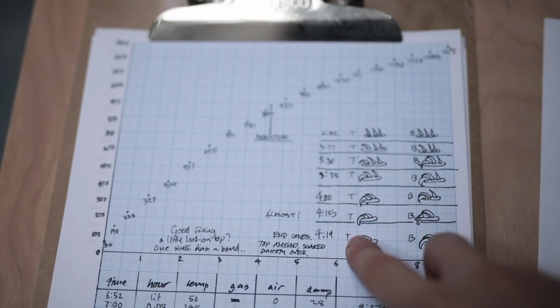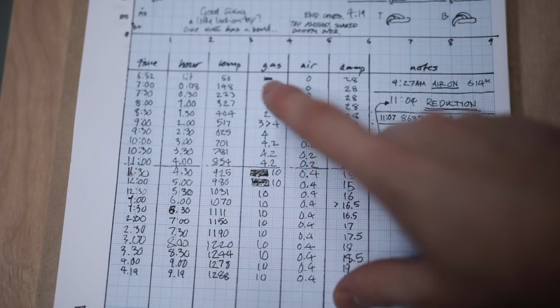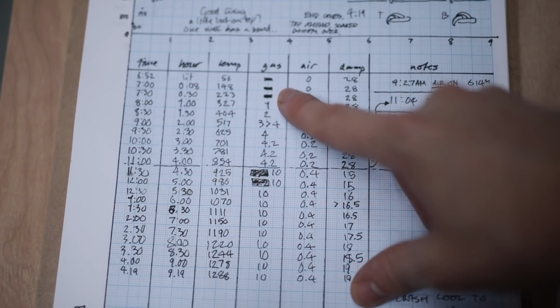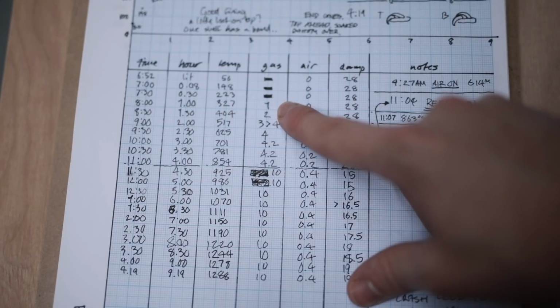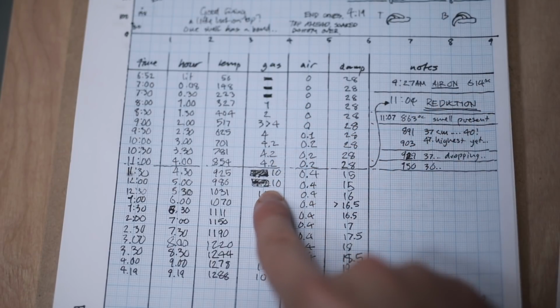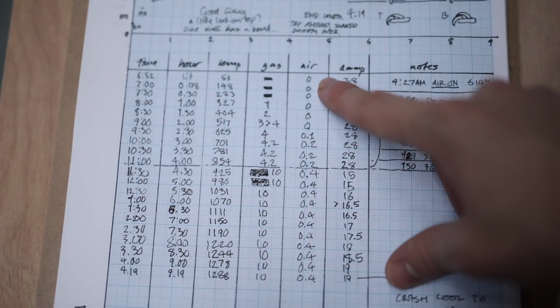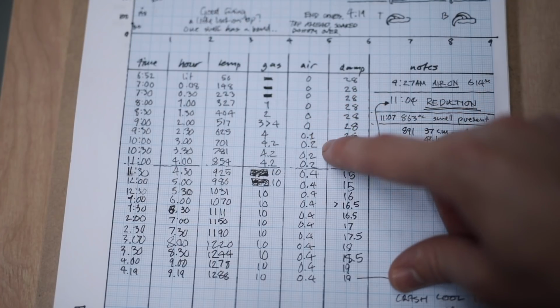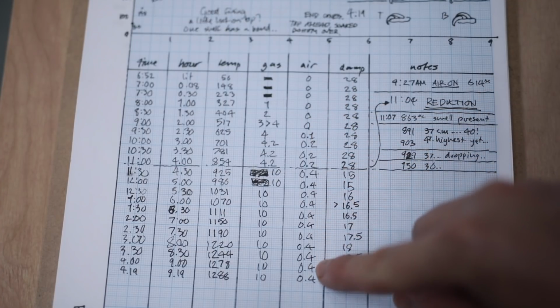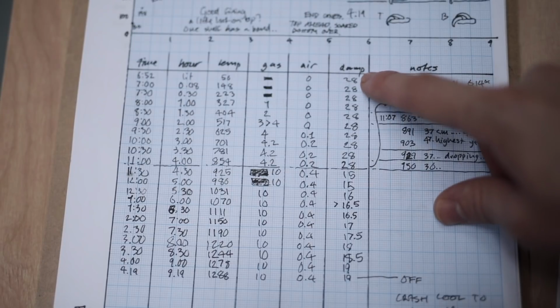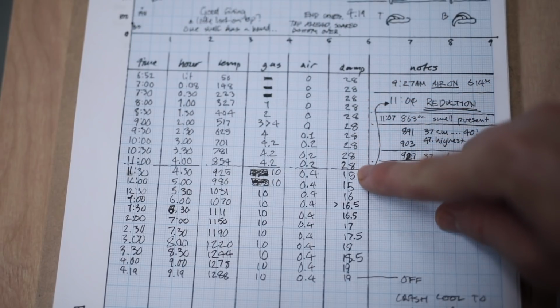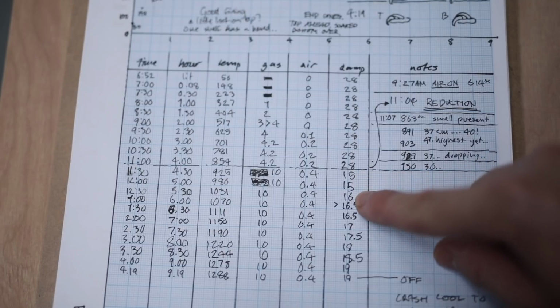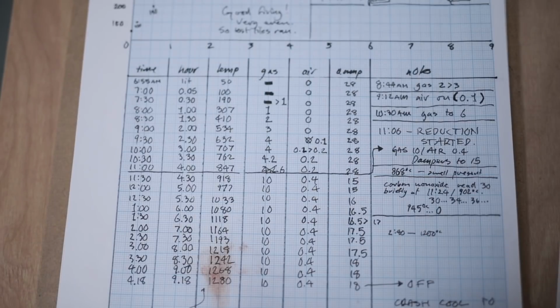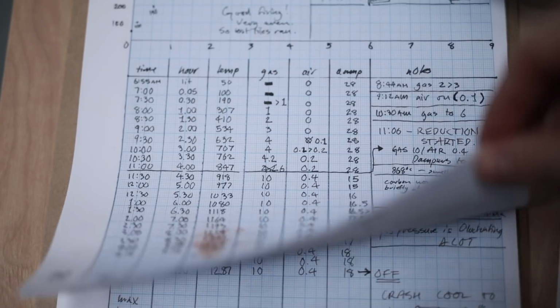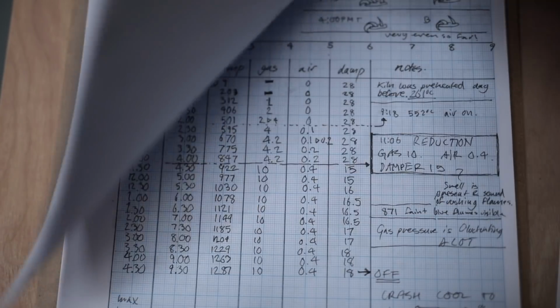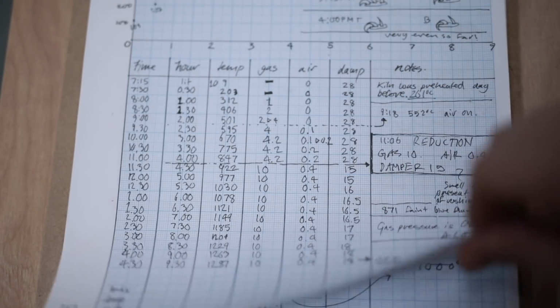Generally the top goes over first, but the bottom always catches up quite quickly. Here you can see how the gas is increased slowly. Excuse my poor handwriting. 10 is where reduction is initiated. As I'm using mains gas too, I also have to have an air compressor to help give the burners and flames enough pressure. It follows the gas, slowly rising. And lastly there's the damper. 30 would be the most open it can be, and 15 is halfway closed. Thereafter it's steadily opened until about 18 or 19, and that's usually when the firing ends.